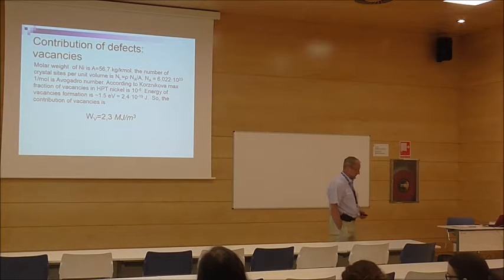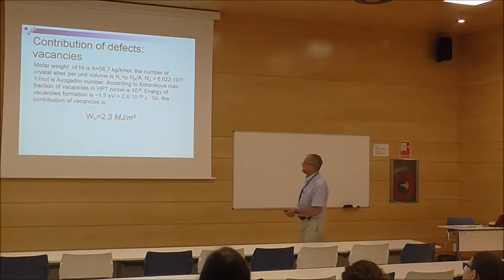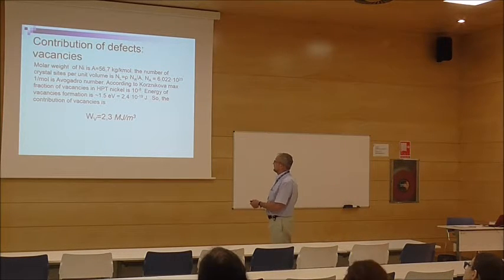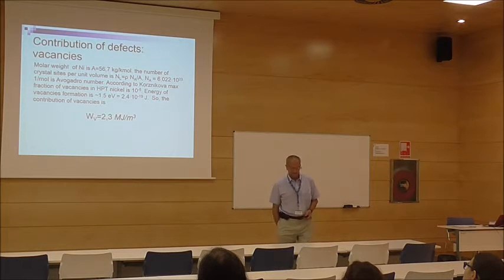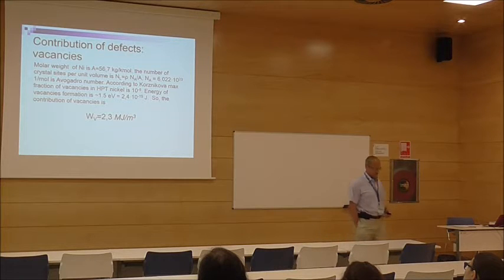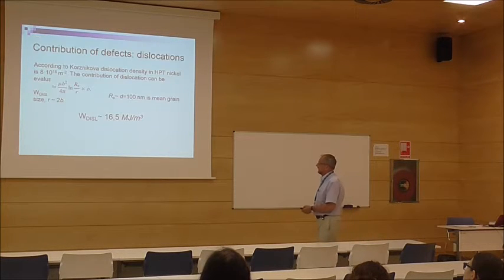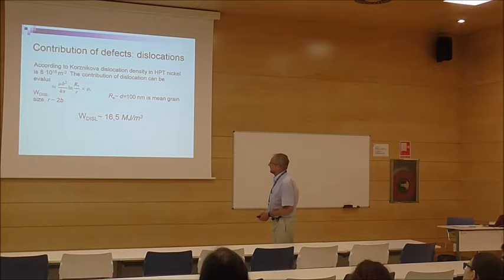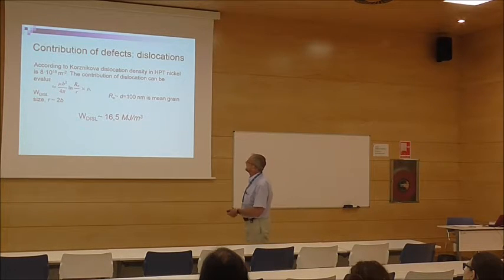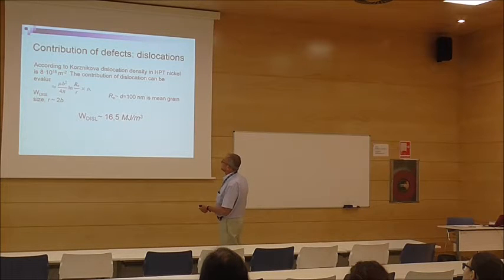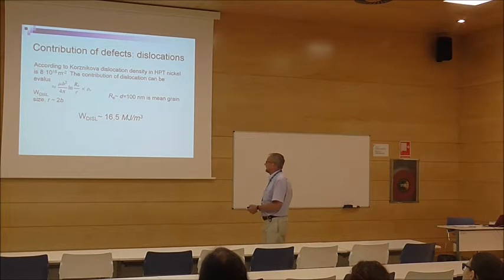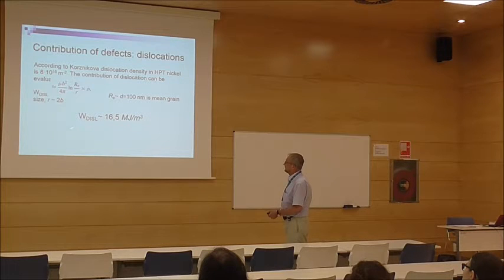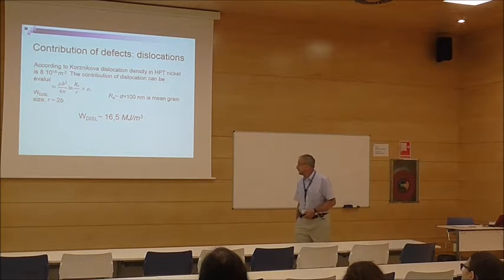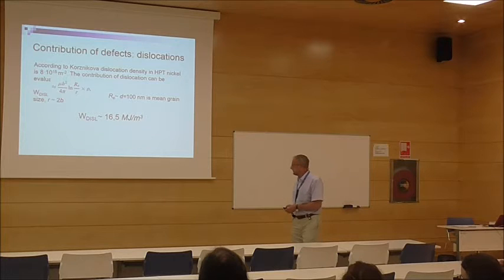So we can use all this data to evaluate how much contribution to the energy could come from vacancies. It's quite easy. Everything is just calculated. It gives 2.3 megajoule per cubic meter. About the dislocations, we can calculate this by this equation, which gives 16.5 megajoule per cubic meter.